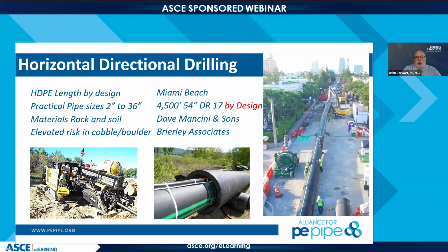We got to put valves in there. So we had to install the pipe, and then we had to have valves that had the strength to take the surge, this being a force main, surge and thermal effects. And you have to look at the time that the surge is going to happen, which is the pump's system. So that's your sequence of one surge is going to occur. And then you look at your temperature difference over a much longer wavelength. You have a temperature difference maybe over weeks or months. You take these into account when you design your restrictions for that valve to keep it in place. So that was the interesting thing, trying to couple these things together.